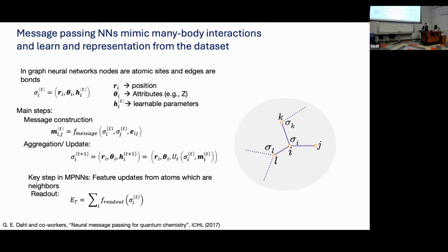So how do we define nodes? It's the distance, the position in space, r. It's some set of attributes that we can assign to it. For example, the atomic number, but that can be a much larger vector of properties related to Z or other properties, for example, electronic structure properties of the atom. And even a set of learnable parameters, h_i. And those learnable parameters are passed through several layers, t. So t here indexes the layers in a neural network.